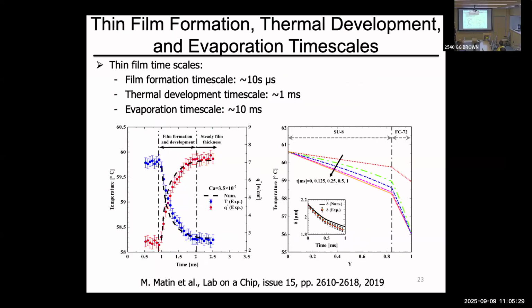So to answer Solomon's question, in the community, people have had access to less complicated experiments, which involve adiabatic experiments. But people don't necessarily give the same amount of credit to those experiments because boiling is not happening. What we realized here was that film formation happens in microseconds, tens of microseconds, but the entire evaporation happens in milliseconds. So you could essentially assume that the formation of the film is adiabatic. You can then remove the heat transfer and understand the fluid from a completely fluid mechanics point of view, and then actually do the experiment.